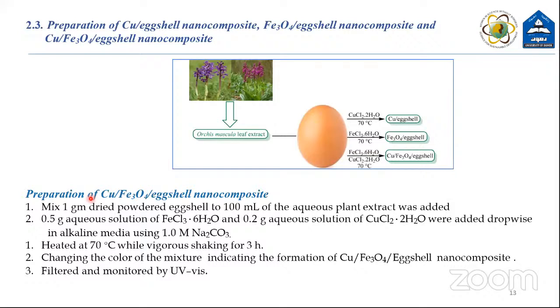Preparation of copper magnetite eggshell nanocomposite is done by mixing powdered eggshell with the plant extract, then adding 0.5 grams of iron salt and 0.2 gram of copper salt in alkaline medium dropwise, followed by heating to 70 degrees centigrade for 3 hours. Change of color of the mixture indicates the formation of the nanocomposite, which is monitored by UV.